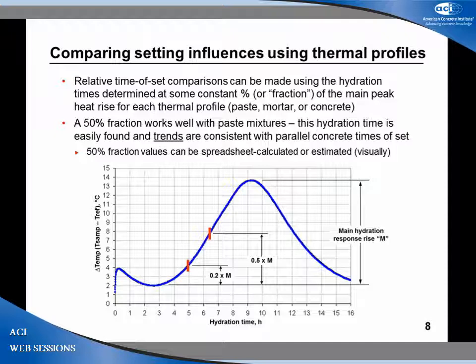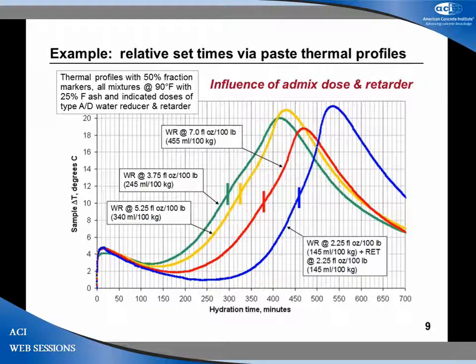If you're trying to actually replicate concrete initial setting times, you could probably do that if you're willing to go through a little bit of fine-tuning on the front end, calibration, if you will. And that number would probably be something in the range of about 20% of that thermal rise. We typically use 50% because it really doesn't matter, and that's a convenient one to use. And here are some applications. Different paste mixtures with different admixture combinations and dosage rates to evaluate the retardation effects of those individual changes. And as it turns out, the hydration time differential, one mix to the next, is very, very close to what happens with initial setting times in parallel concrete mixtures. Just add the aggregates, put up the concrete mixtures, and do the penetrometer setting times, and you get different numbers, but the change from one mix to the next turns out to be very, very close to this.